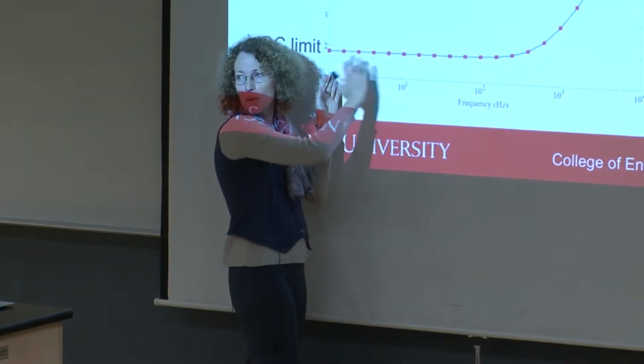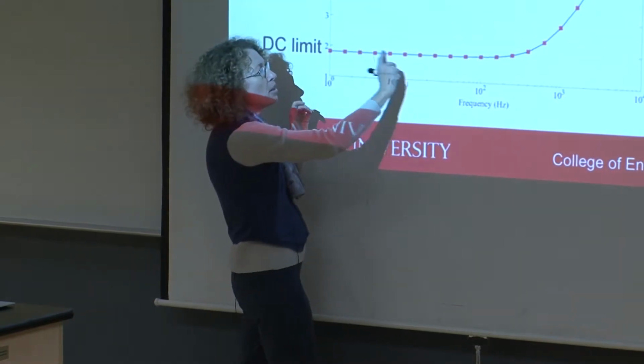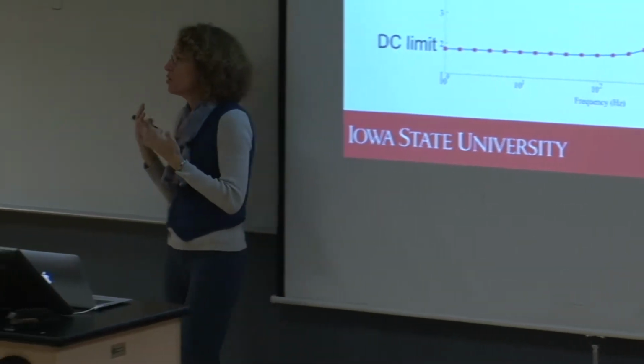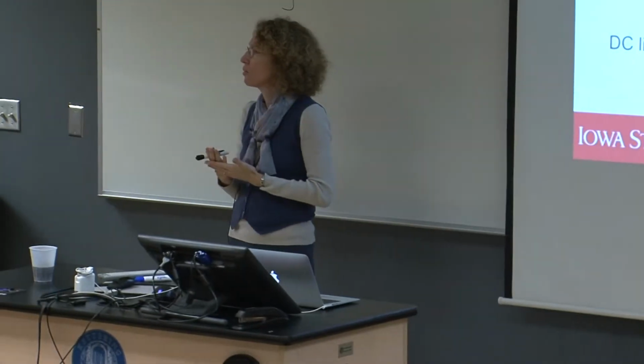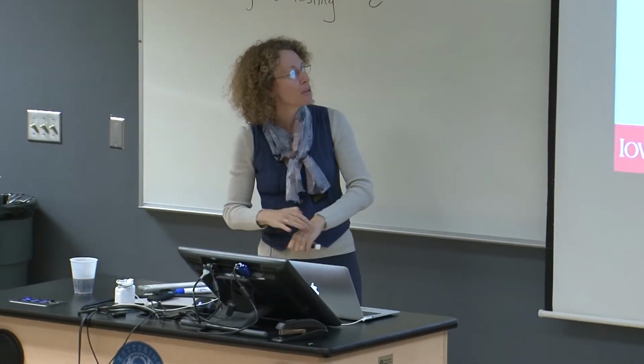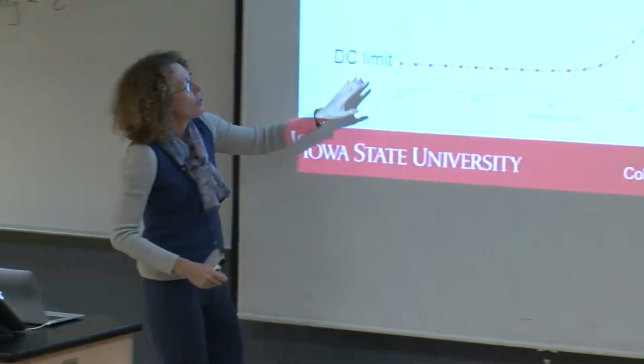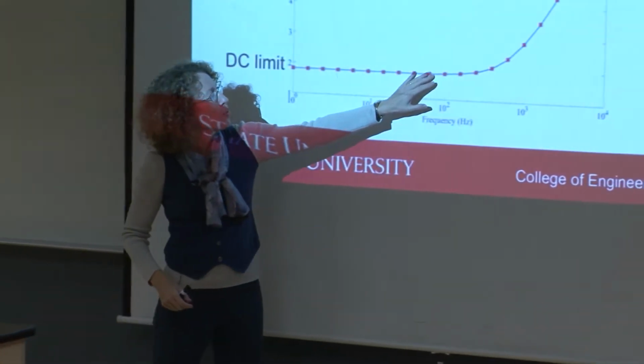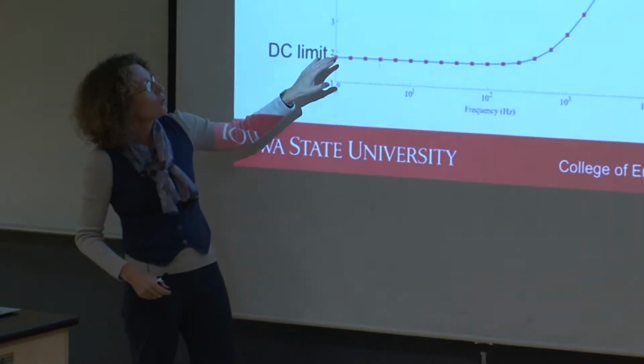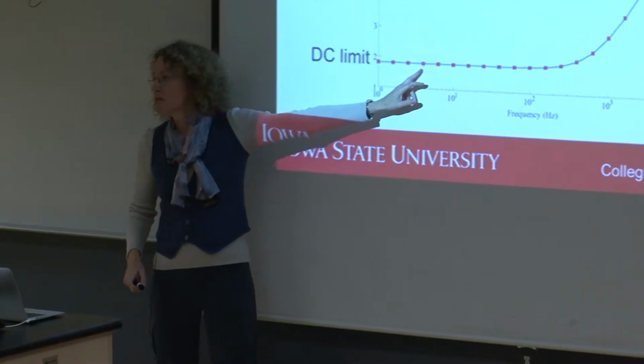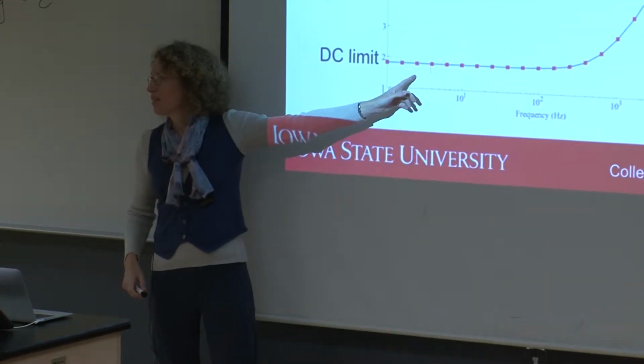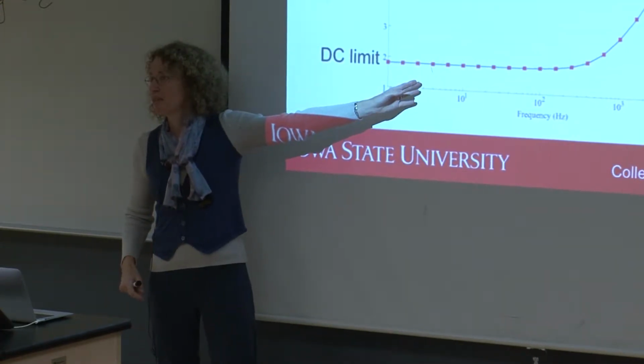This is what we call the DC regime, the quasi-DC, okay? Because everything is just one number. The geometry doesn't matter, okay, until you get up to higher frequency. So this is the DC limit. This was what would be measured at low frequency. These red crosses are actually experimental data, and the blue line is our theory, okay?